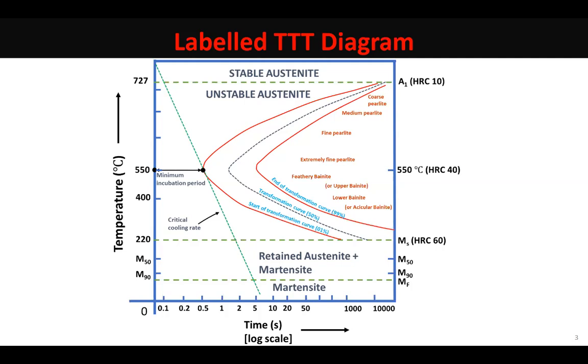It can easily take this amount, 0.77% of carbon in it. But think about alpha iron, maximum solid solubility is 0.02 at 727. At room temperature or at 200 degrees centigrade, solubility is about 0.000 something.